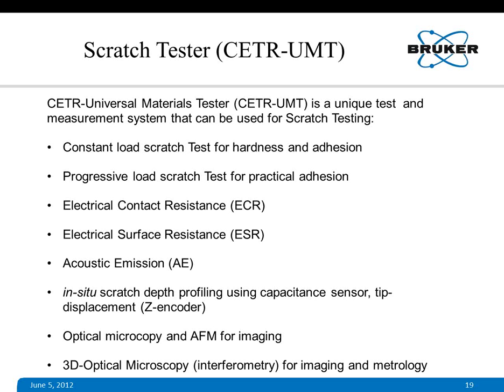Bruker has a scratch tester. The model is known as CETR-UMT, and the CETR-UMT can perform almost all kinds of scratch testing. It can perform constant load scratch tests for hardness and adhesion, progressive load scratch tests for practical adhesion, and it can measure several things like electrical contact resistance and electrical surface resistance. This is very important when we deal with an electrically conducting coating on a non-conducting surface.